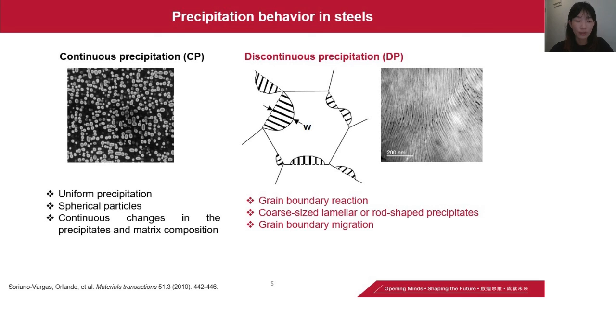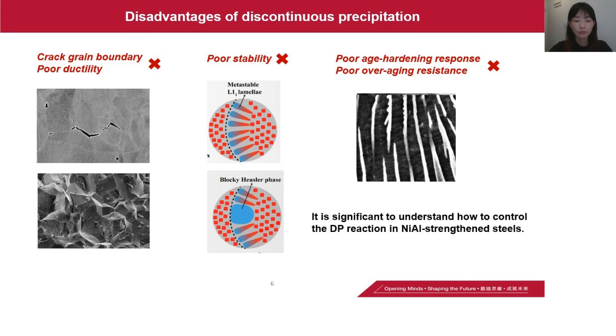In precipitation strengthened steels, there are two precipitation modes, namely continuous precipitation and discontinuous precipitation. Continuous precipitation refers to the formation of spherical particles in the matrix, and discontinuous precipitation refers to coarse rod-shaped precipitates formed along the grain boundaries, which grow into the grain interior and result in the DP colonies.